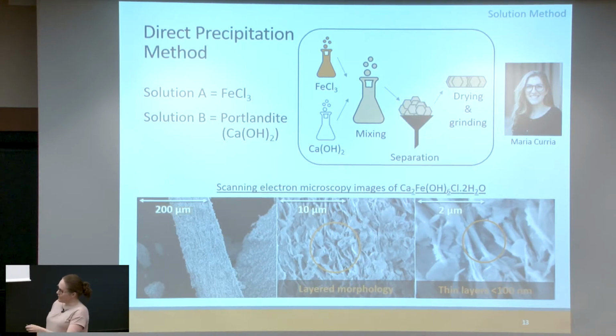And so down here are scanning electron microscope images of the material. It's got these flat plate-like shapes, but if you zoom in on it, there's this layered structure to it, which is very much indicative of the layered double hydroxide, where the layers for the actual individual particles are less than 100 nanometers. And then if you zoomed in again, well, you can't see it, but there would be that stacking of the atoms that we saw with the hydroxide layers.